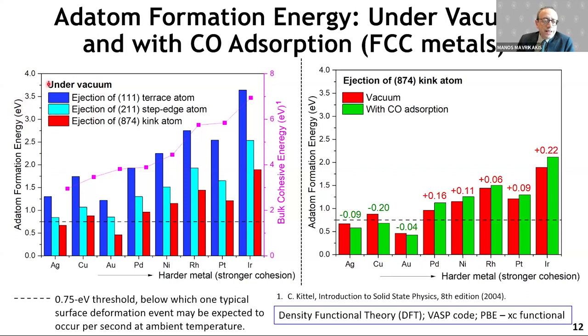Okay, and it is under vacuum that we calculated the energy needed in order to eject an atom from a terrace, or from a step edge, or from a kink atom. So for each metal, you have three different sources, and obviously the shortest bar is the red one, which corresponds to ejecting the least coordinated kink atom compared to the terrace and the step edge atom. So this is not surprising news.